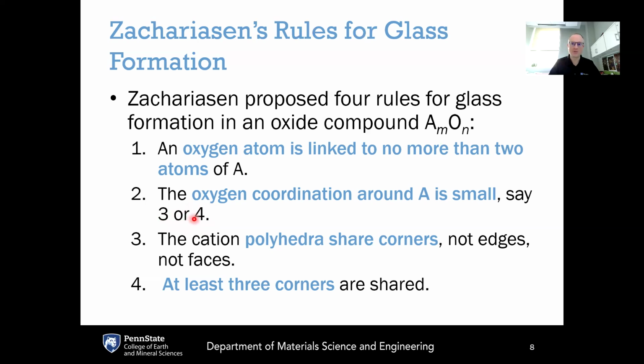And in order for that network to extend in 3 dimensions, we have to have an oxygen coordination of 3 or 4 here. Otherwise, if it's less than that, you could end up with just flat sheets or long rods instead of networks that extend in 3 dimensions. Okay, so if these first 2 rules define the short-range order, the third and the fourth rule define how these basic structural units are bonded to each other.